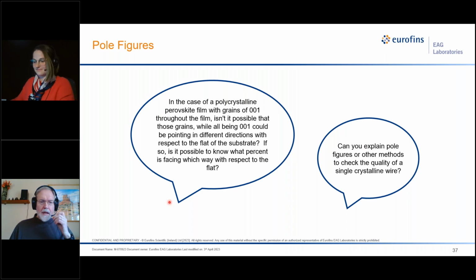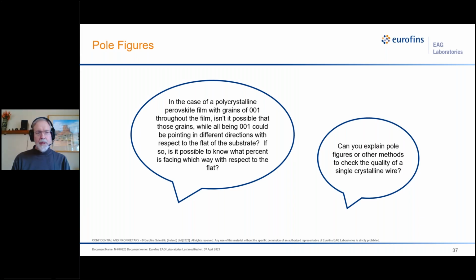Thanks, Stephanie. Sometimes the texture is complicated enough that the peak ratio method or rocking curves doesn't give you a complete answer. An example of that might be something like when aluminum metal is rolled into a sheet. So in this case, we use pole figures. This technique can measure any kind of texture, any fiber texture or more complicated ones. And the way this works, Stephanie, if you can go to the next page.